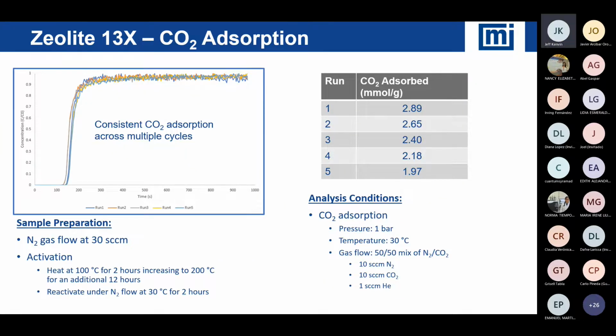Okay. So if we look at a really typical application, and this seems to be now the standard for breakthrough, and especially with CO2, people will show you 13X zeolite with CO2 adsorption. They'll typically run multiple cycles, and we can calculate the quantity of CO2 adsorbed. You see that on the right side for different cycles. This is a nice piece of breakthrough because you can program your breakthrough experiments to run multiple cycles and watch the performance of the material. Does the material degrade? So this is really simple, just CO2 and the zeolite.